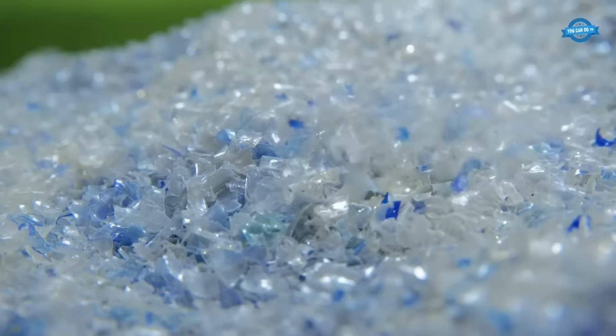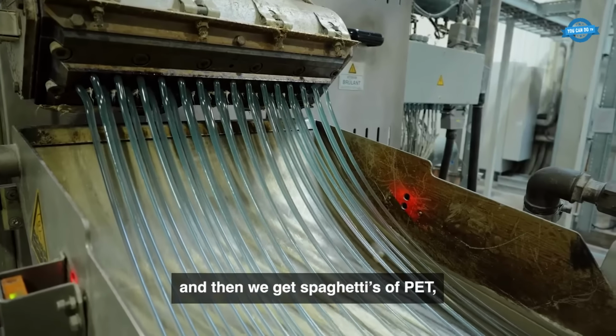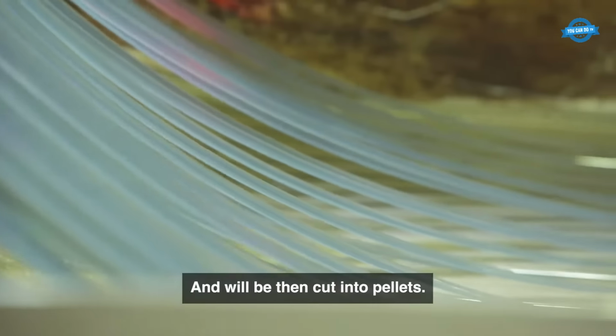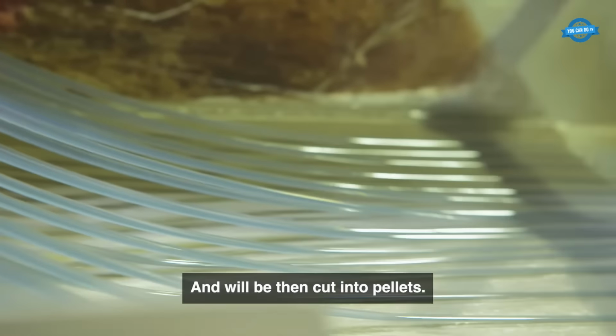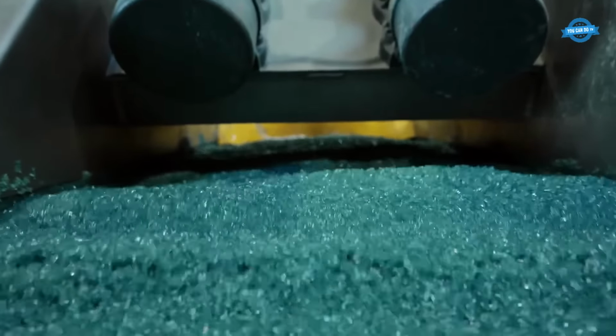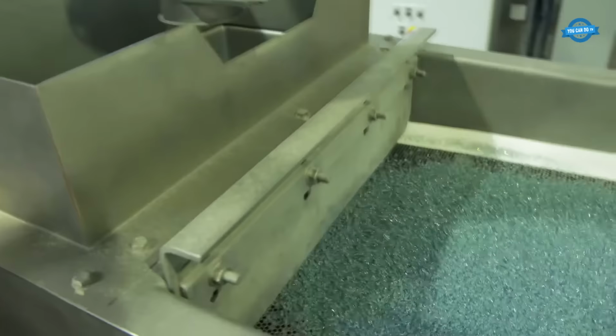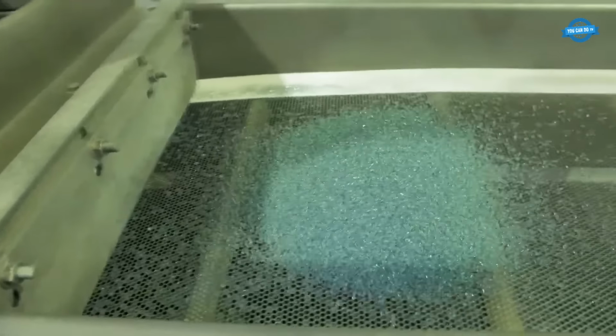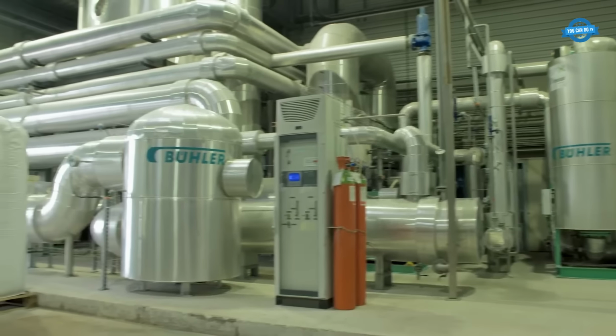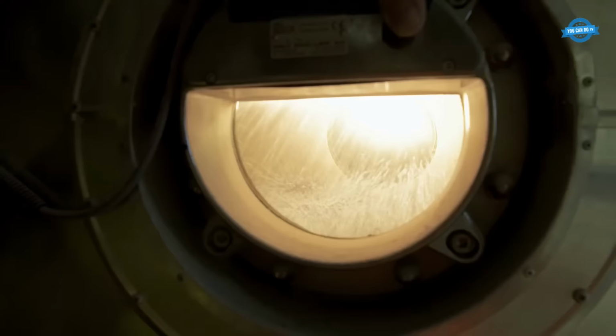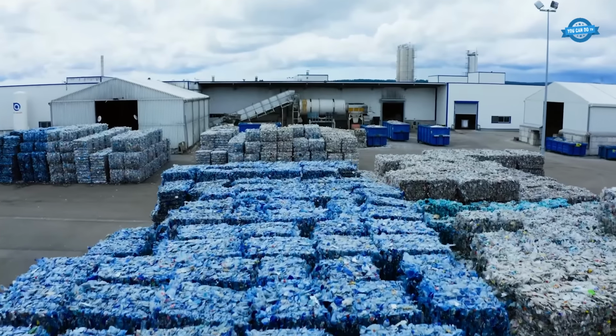The flakes enter a silo, are dried, melted, and filtered, then extruded as continuous strands, spaghetti, of reformed PET before being cut into pellets. A decontamination unit running under nitrogen brings those pellets to food-approved standard. One plant in eastern France processes approximately 4 million bottles per day. The material is made to be remade.